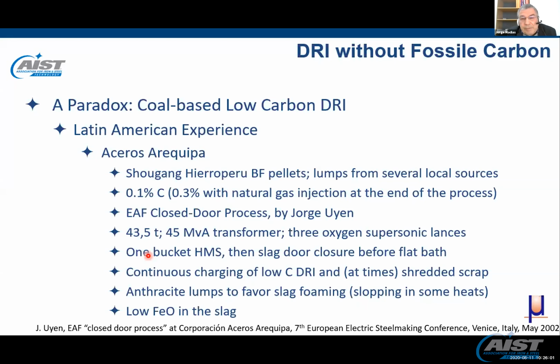43.5 tons the furnace, 45 MVA the transformer, 3 supersonic lances, and they used to charge 1 bucket of HMS, then slag door closure before flat bath, continuous charging of low-carbon DRI, and at times they also continuously charged shredded scrap. Anthracite lumps to favor slag foaming. They used to have some kind of BOF-like slopping in some heats through the holes of the roof. Low FeO in the final slag, in the EAF. So they worked like this for several years.